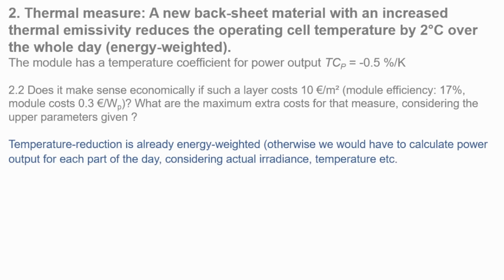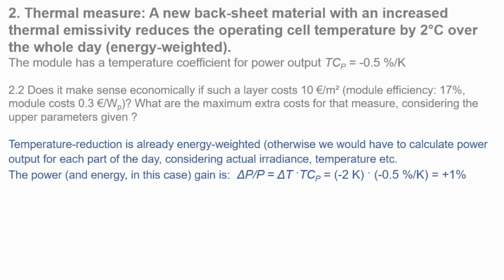So temperature reduction is already energy weighted. Otherwise we would have to calculate power output for each part of the day considering actual irradiance, temperature and so on. So we have the power and the energy in this case. The relative increase, delta P divided by P, is the relative temperature change times the temperature coefficient for power, and that's 2 Kelvin. The temperature coefficient is minus 0.5%. So you have got 1% more power.